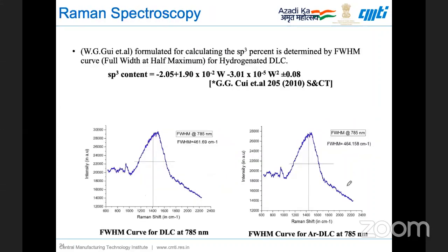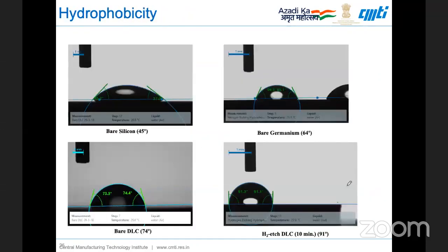So let me not worry about this and show you the hydrophobicity that we have achieved. We can play around with it. If you want a wet surface that needs some sort of wetting, we can achieve that, as well as a hydrophobic surface. This is useful when you coat diamond-like carbon on solar panel protection glasses. You have rain, sand, abrasive particles, and you want to self-clean it. So you have to form beads. If you are able to treat it with a very, very fine thickness of DLC, there is some transmission available, as well as the water beading out, cleaning the surface. That is where these sort of applications are useful.